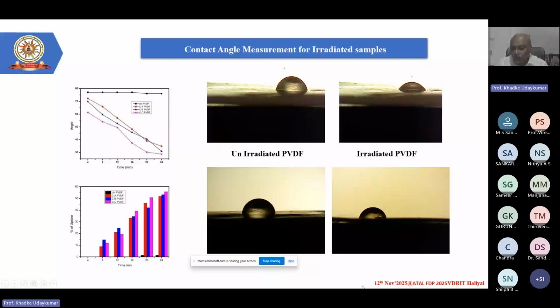Now you see that this has stopped on the surface. This is the unirradiated surface, and this is the irradiated surface. Because of irradiation, the water molecule is going to the inner side, which eventually tells us that yes, the porosity has been created. Another way: the moment you have porosity, you need to understand whether this separator is taking the electrolyte up or not. Electrolyte uptake is another important phenomenon to understand whether the separator is good or not. We saw that the electrolyte uptake is also coming in proper order.